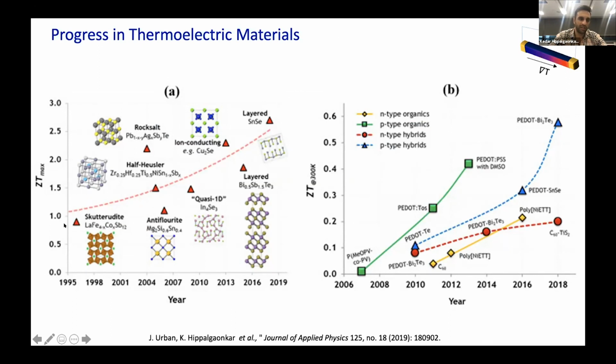So if you look at all materials that have been discovered, right, you can see that the ZT value doesn't go up very large. It goes from about 1 to 3. There are various different materials that are there, both in the inorganic space and the organic space. And typically a ZT of about 1 at a temperature of 400 to 500 Kelvin is about 10% efficiency. So a ZT of infinity, which is theoretically possible, is equal to the Carnot efficiency for any thermodynamic cycle. So the upper limit to this ZT is actually infinity, but there are very few repeatable experiments or theoretical predictions that go higher than 2.5 to 3. So the real game changer is how do we actually hit that thermodynamic limit of actually pushing up the ZT